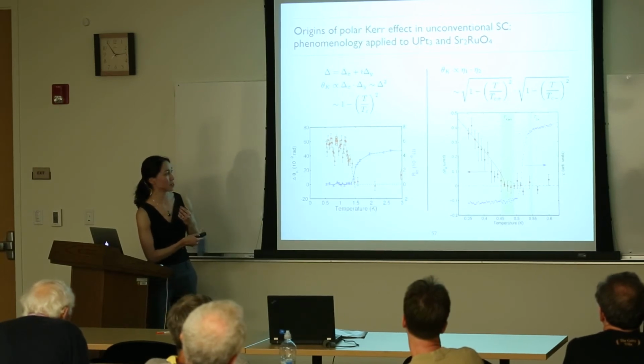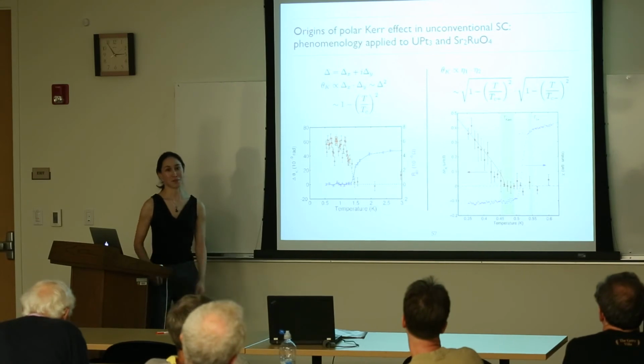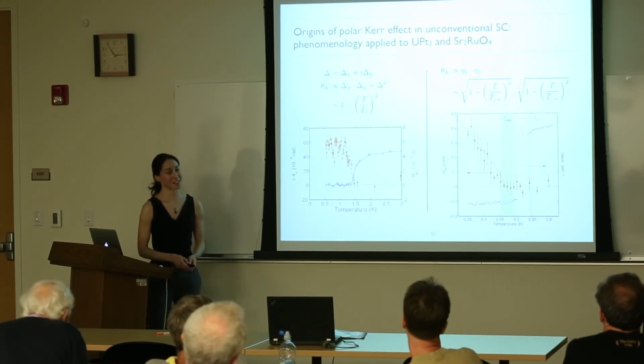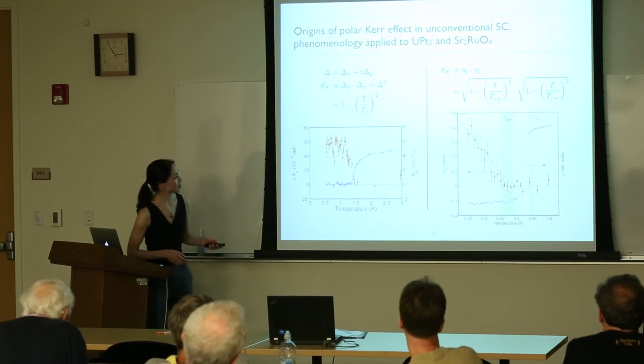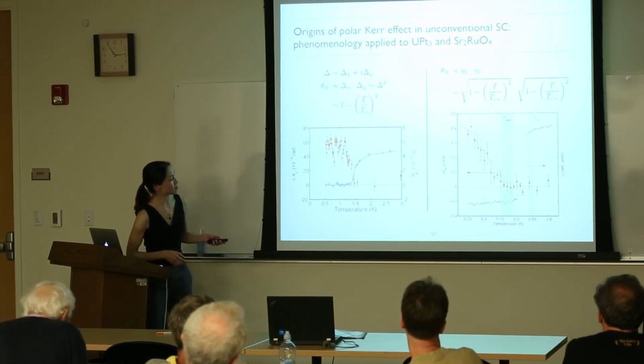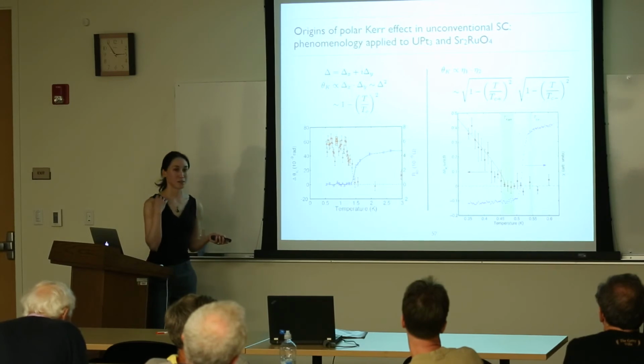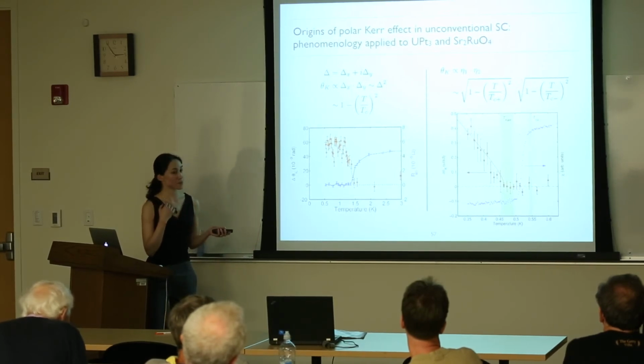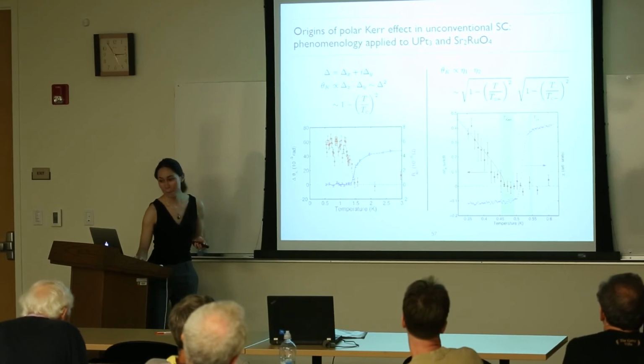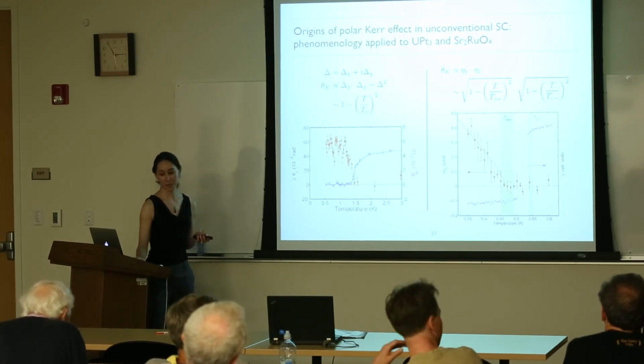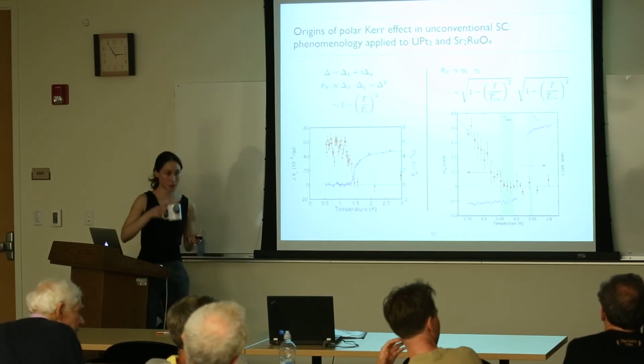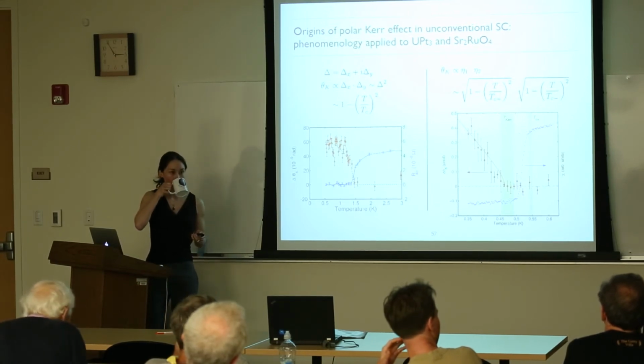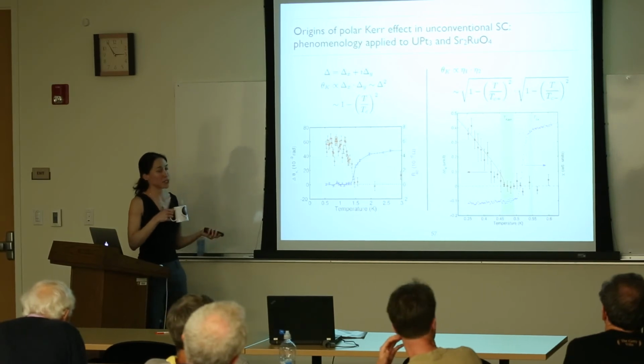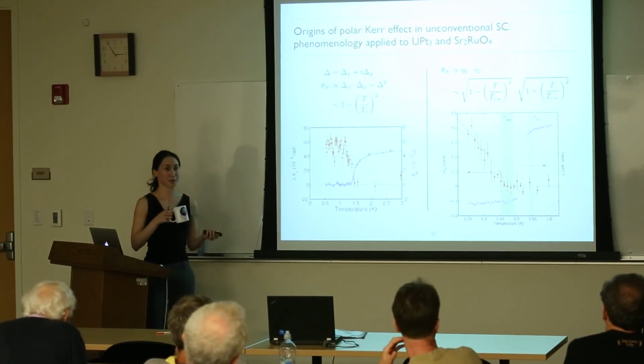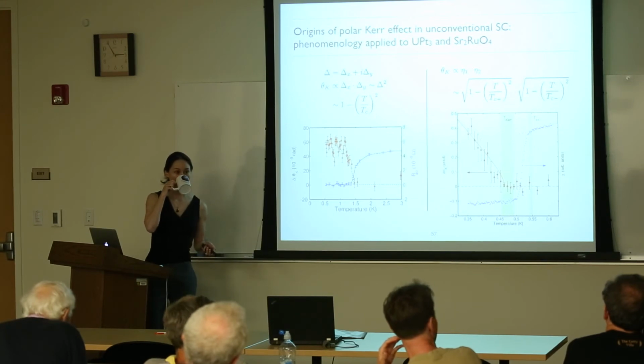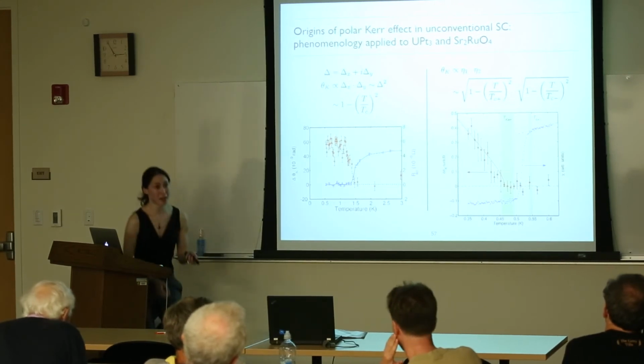And it makes a curve that looks kind of like this, which, you know, is not inconsistent. Where's Tc minus? It's around here, somewhere in the range of 450 to 500 millikelvin. And you know that in this sample the resistive transition is at the higher temperature. That's right. Well, we did mutual inductance because this is a really good metal and resistance is hard to measure. But yeah, Bill's group also measured it.